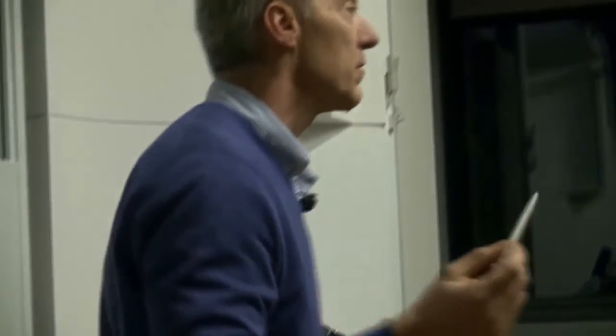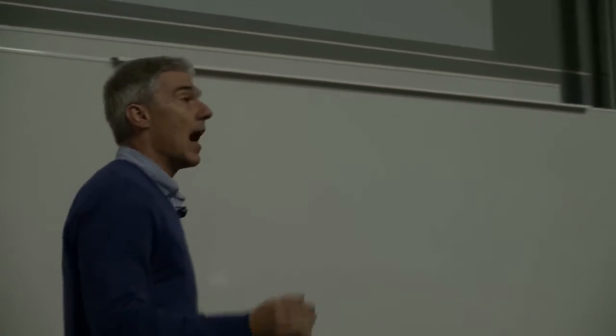By rastering this very sharp tip across my surface, I can record the deflection and use that to build up a surface profile map, a map of the features, a bird's eye view of moving across the surface, really. It doesn't get subsurface, and it doesn't get into cracks that are right inside caves, as it were.